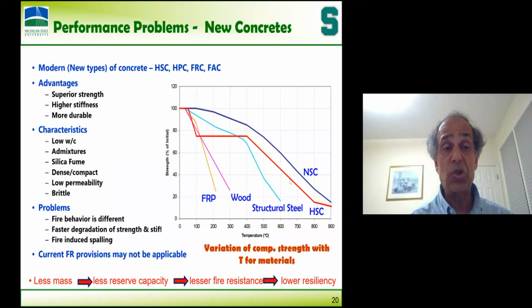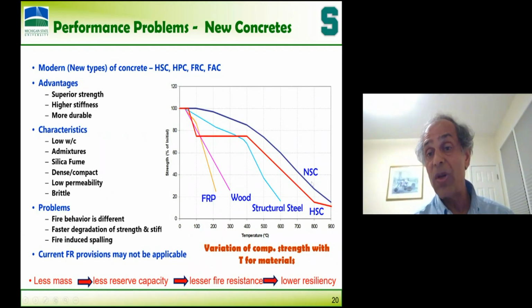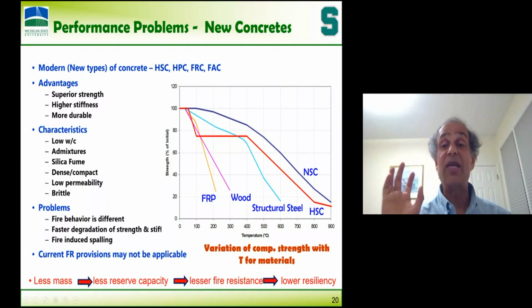It's susceptible to two things. One is the strength of the newer concrete. See this red line, this is how the strength drops with temperature. Look at the normal strength conventional concrete, it slowly drops. So this is the major problem. The second bigger problem is the occurrence of so-called fire-induced spalling.